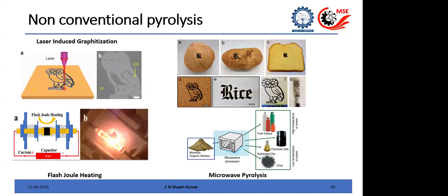One thing is the laser induced graphitization. You can use laser to graphitize polymers as well as biomass to highly graphitic carbon within very short time, because it is fast. And also there is something called flash joule heating now, because you give very high power and high voltage for a very short time, and then you can convert these things into highly graphitic carbon. People have also used microwave pyrolysis, because carbon is microwave active, so you can actually heat carbon with microwave. Some examples, then I think we'll stop.